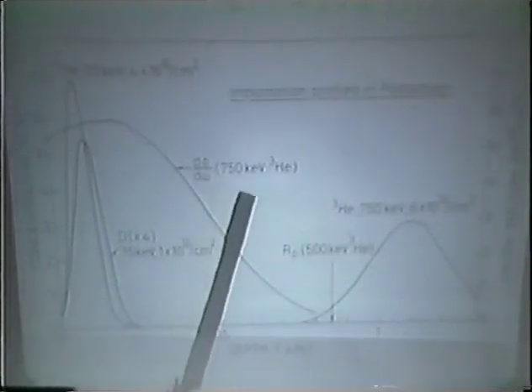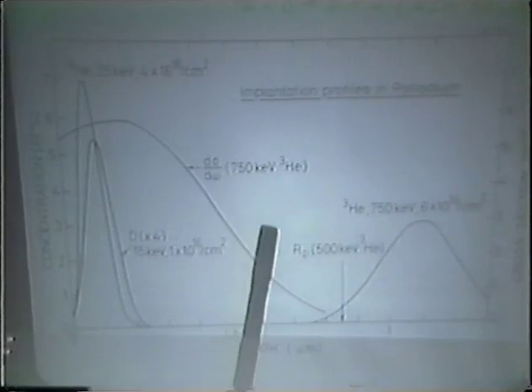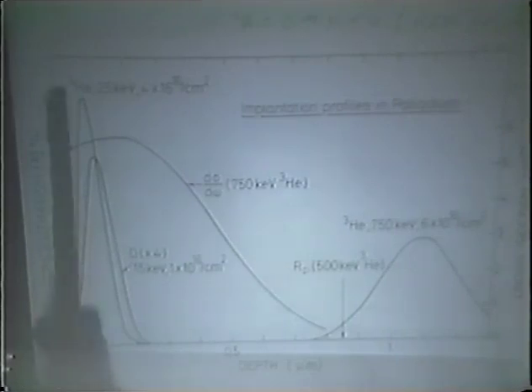You can see that as long as the helium-3 ion is losing energy in the crystal, the nuclear cross-section decreases here, and you can see that we essentially probe hydrogen within the first half micron with this technique. You can also see that the analyzing beam ends up at a range of the order of 1 to 1.1 micron. In some cases, we also pre-implant our crystals prior to the deuterium implantation with 25 keV helium, typically at a fluence of the order of 4 times 10 to the 16.